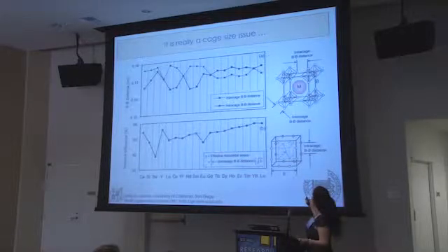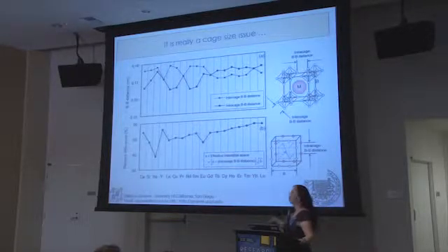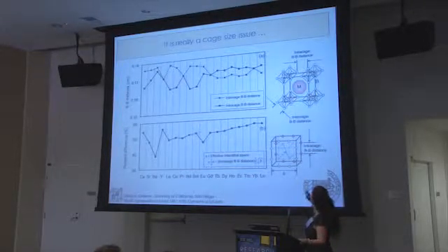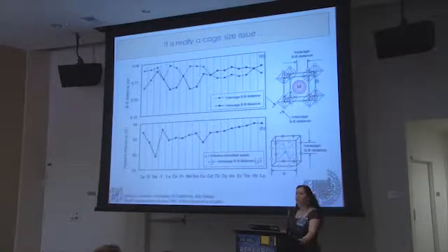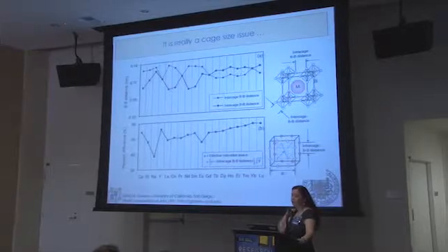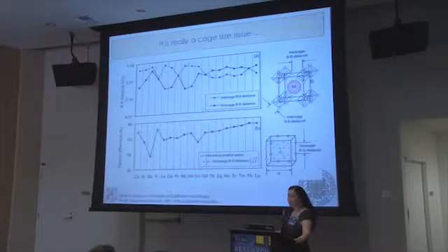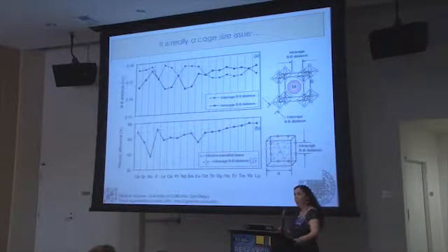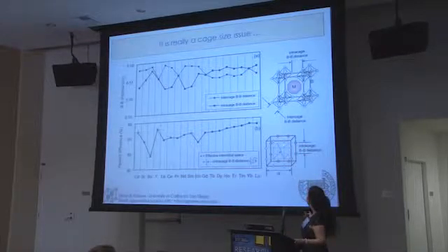And so the intracage boron-boron distance is fixed. Those boron octahedra are all the same size no matter what you put inside. And then the distance between boron octahedra, this distance over here, is also fixed. So if you look in the literature at the size of the unit cells of these crystals, you're going to find that they really don't change no matter what you have on the inside. And so the issue is, if the cage does not change in size, what happens when you put something in here that is very, very small?